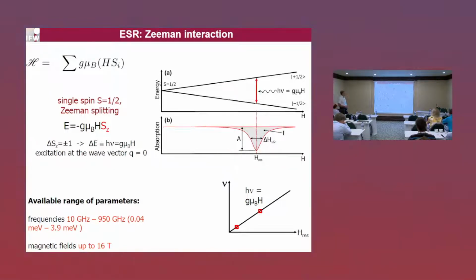And if one plots the resonance field on this frequency versus magnetic field diagram, one will obtain a straight line originating from the origin, and the slope of this line is determined by the g factor. The g factor is a very important spectroscopic quantity. It's fundamental because it relates the angular momentum of a quasi-particle with its magnetic moment. In our lab we can change the excitation frequency by two orders of magnitude, from 10 gigahertz to almost 1 terahertz, which corresponds to energies from 40 microelectron volts to almost 4 millielectron volts. And this is the relevant energy scale for looking for spin waves.